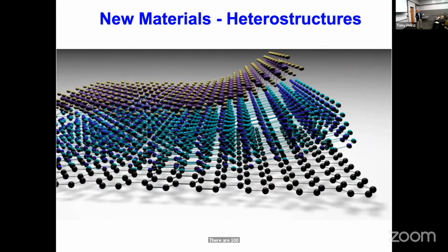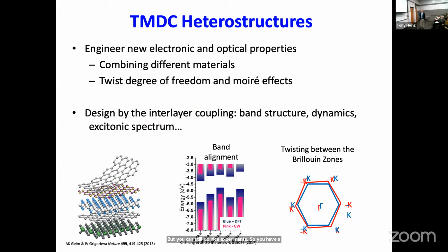So why is that? It's because there was some pump oil, but the pump oil was extremely mobile. And basically when you stack the things together, you get regions that actually look like this, where the materials are actually in ideal contact. Now, there's a part that doesn't appear in the picture in the paper, which is like a bubble of contamination, but you can still do nice experiments. So you have a huge number of possibilities.